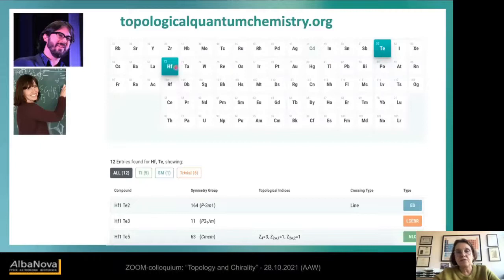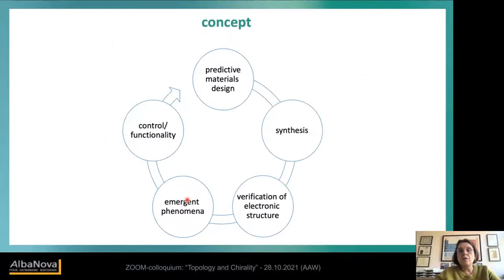I took hafnium telluride, for example, and I told you it's already on the lower part of the periodic table. So if you see from all the different combinations of hafnium and tellurium, you find a few which are trivial, but you find also many which are topological, and one semi-metal. You see already from this ratio that topology is not a rare concept. So what do we do?